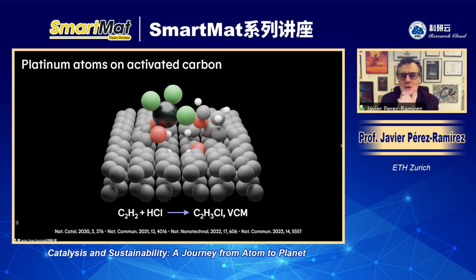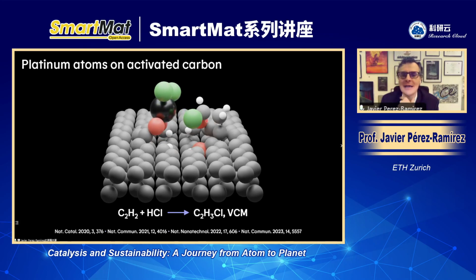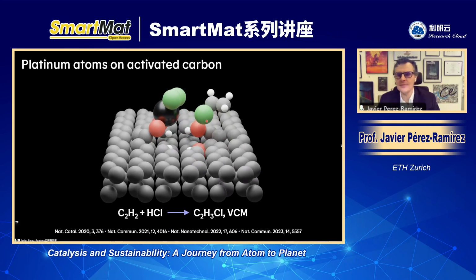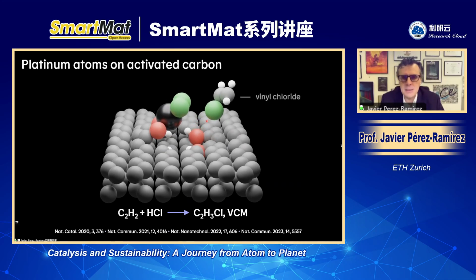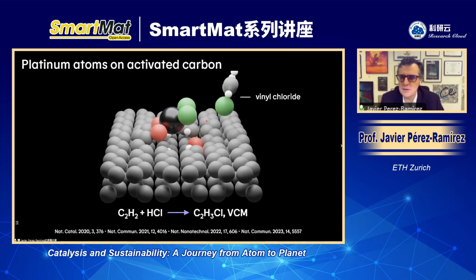And acetylene is never adsorbed on the single atom. It's adsorbed on the neighboring site of the carrier, of the support. And so then that is producing the coupling. So basically the transfer of the chlorine from the platinum single atom to the acetylene moiety that is adsorbed on the carbon. The reason why I show you this is because it clearly shows that the platinum atom doesn't do the whole job on its own. It requires the host to activate the triple bond.